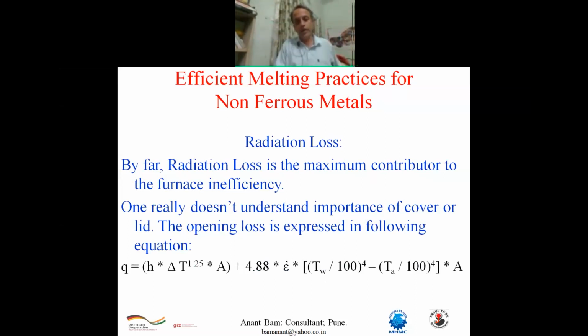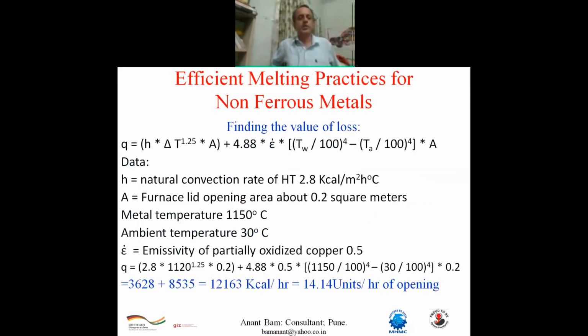Now we replace the figures. Natural convection rate of heat transfer for air from any hot surface is 2.8 kilocalories per meter square per hour degree Celsius. A is the furnace lid opening area. Let us assume it as 0.2 square meters. Metal temperature, our tapping temperature, 1150 degrees Celsius, ambient temperature 30 degrees Celsius. Epsilon, emissivity of partially oxidized copper, is 0.5.